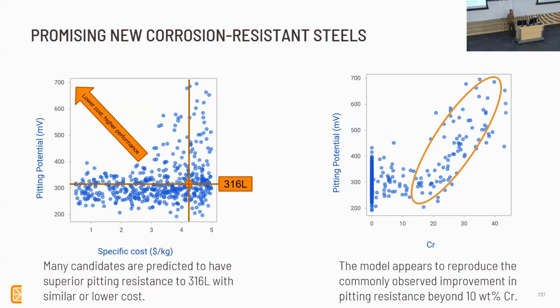And it's a very common rule of thumb with stainless steels that chromium is the secret sauce to making a stainless steel stainless. And that usually happens at around 10% weight percent of chromium. That's a very common metric that people use. You might have all seen this in your Material Science 101 textbook. Well, the data from these new alloys actually bears that out, where you can see beyond about 10%, the pitting potential increases quite a bit. So you're getting physically consistent behavior from this machine learning model to what we all kind of know from our material science backgrounds. So it's important to check these kinds of things to make sure your machine learning model is giving you relevant and sane results.